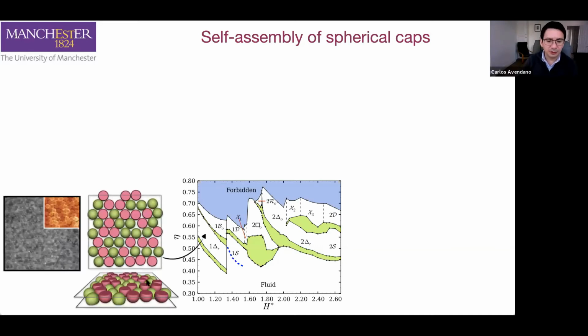What we observe at very strong confinement is that the particles cannot rotate. They can only move in 2 dimensions. And what we observe is that the system forms this hexagonal lattice. This is very similar to what you will observe with the spheres. And it makes sense, because if you look at two particles that are close to each other, the flat facets don't see each other. They will only see the spherical shells. So the particles effectively think that my neighbors are spheres. So they should pack in the same way as spheres will pack. And that's what we observe here.